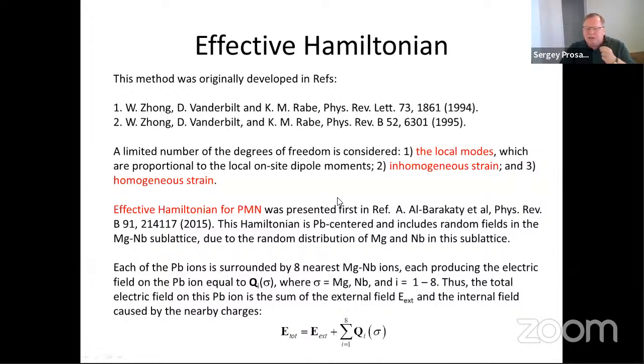Our first example is lead magnesium niobate, PMN, which is a relaxor, and the effective Hamiltonian for this material was created in the Arkansas group, so this is the reference. I should say that the local mode in this Hamiltonian is centered on lead ions, and it includes random fields on lead ions stemming from the surrounding niobium and magnesium ions. And this field is random because niobium and magnesium are randomly distributed in their sublattice, and they have different charges.